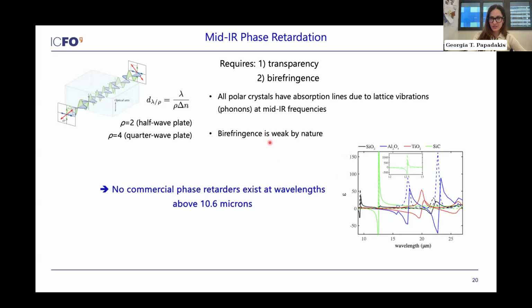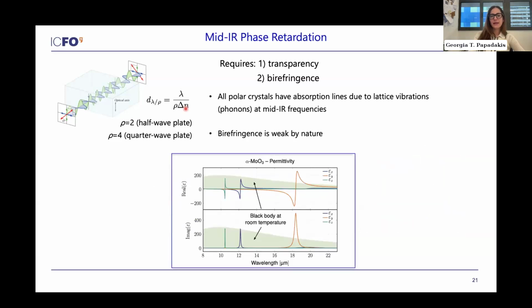And also the birefringence of most anisotropic materials is actually very weak in the mid-IR. Now, this means if you look at this equation here, where delta n is the birefringence, that I would need a very, very thick phase retarder in order to achieve half-wave plate or quarter-wave plate operation in the mid-IR.